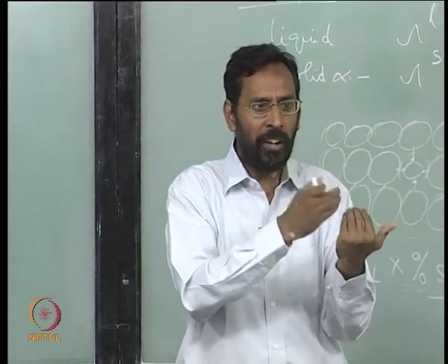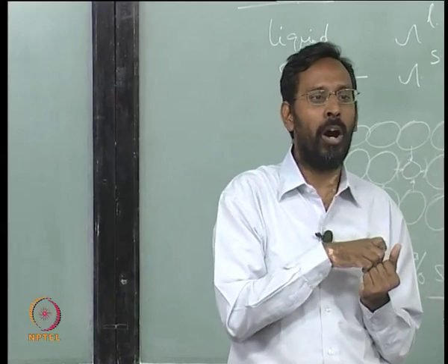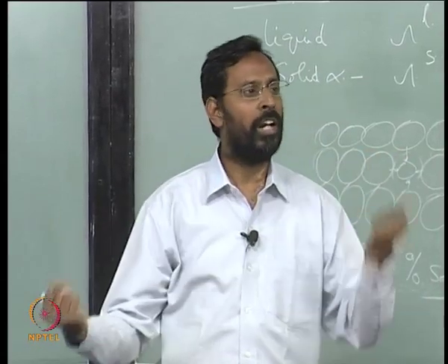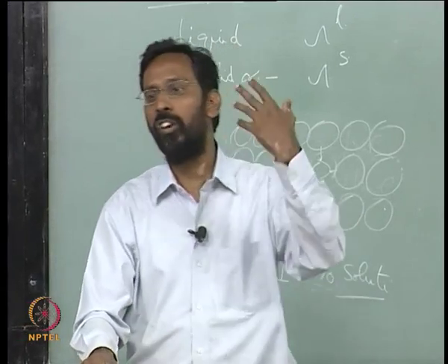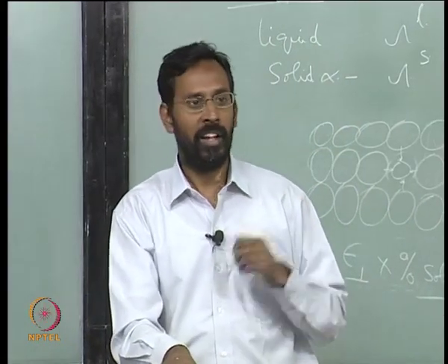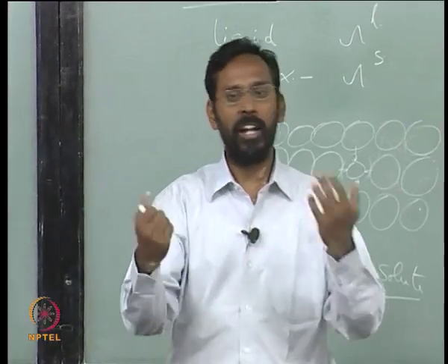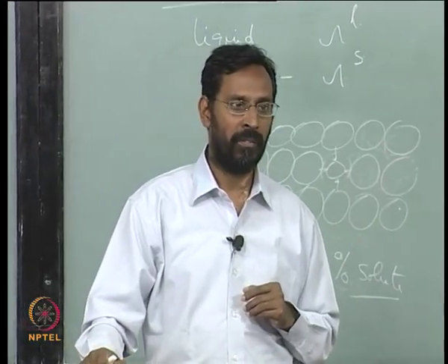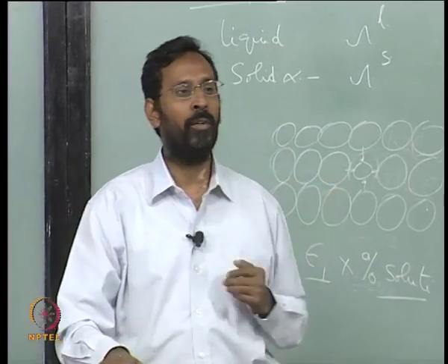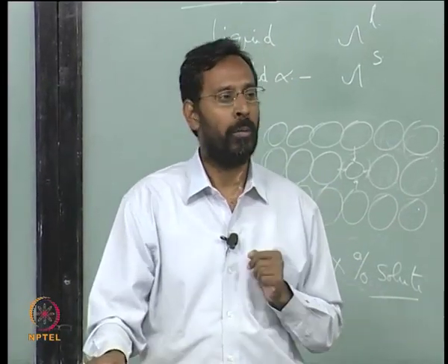So the difference between chemically ordered and chemically disordered is only in terms of the diffraction patterns. You will see extra spots called superlattice reflections in a chemically ordered structure, and in a chemically disordered structure you will not see these extra spots, and you would only see the fundamental reflections. Any of you who have read X-ray diffraction will know more about it.